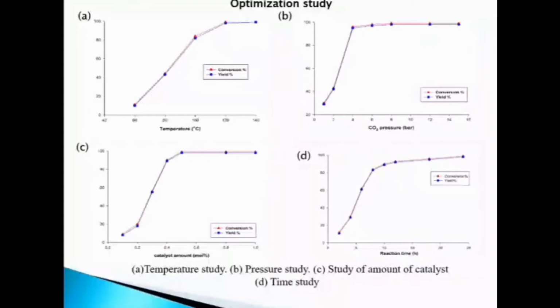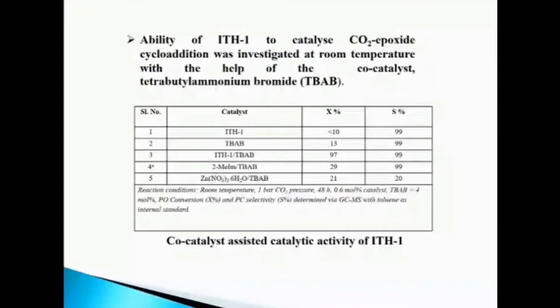The ability of ITH1 to catalyze carbon dioxide conversion was investigated at room temperature with the help of co-catalyst tetrabutyl ammonium bromide. Neither ITH1 nor TBAB alone produced any appreciable PO conversion at room temperature. However, the binary system of ITH1 and TBAB manifested an excellent conversion of 97% of propylene oxide with 99% PC selectivity at room temperature, 1 bar carbon dioxide pressure in 48 hours.